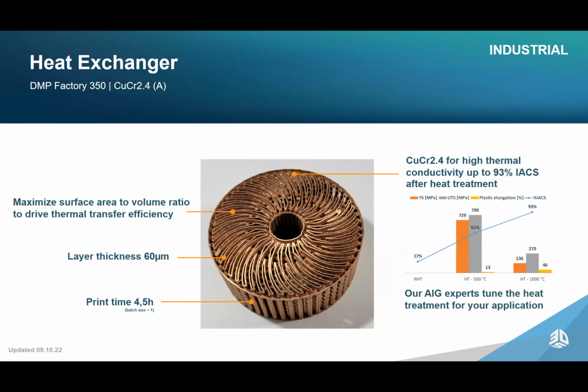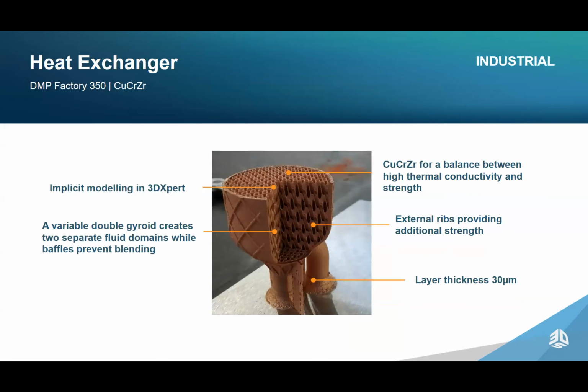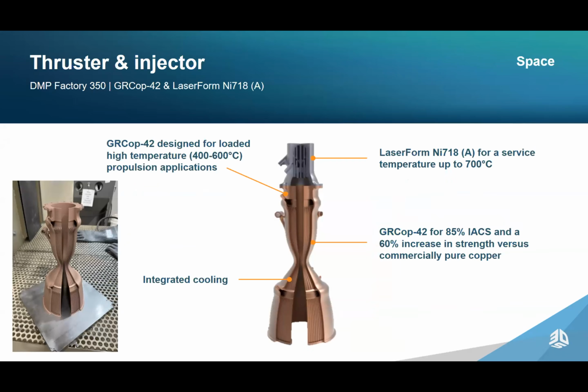I'm going to slide through a couple more of these again. Heat sinks. There's a CuCrZr, copper chromium zirconium heat sink. And of course, we have to show a GRCop-42 and 718 combo. So in this case, we are able to start and print on top of a flat surface. So if we print this propulsion component, we're able to actually re-index on top of it and continue printing, or it could be assembly. And this is a test we did of cladding and printing with a multi-material on top of it.